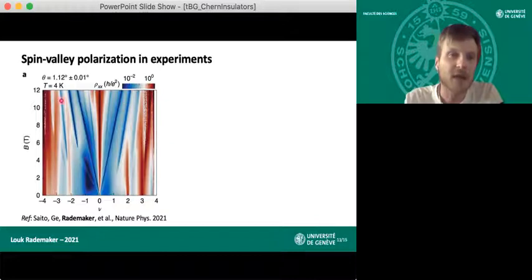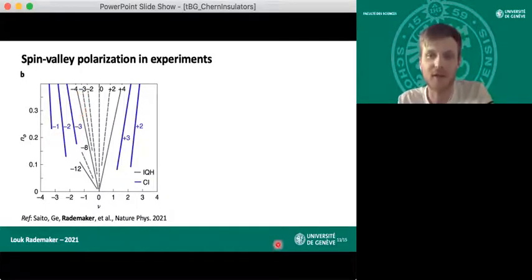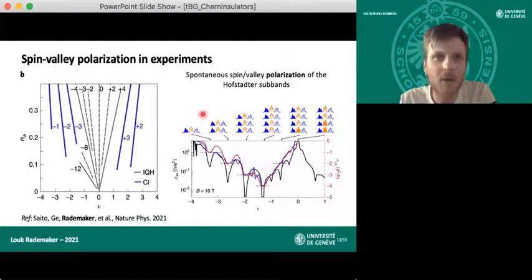And rather than staring at this picture, we can extract the relevant states out of it. Each of these lines corresponds to a Chern insulator state. Here with this cartoon picture, you see it's indeed this sequence of -1, -2, -3, -4 Chern insulator states. I can even drive that home a bit more by looking explicitly at how this data looks at, for example, 10 Tesla, which is about 2/5 flux, where we see that you get a -1 state,